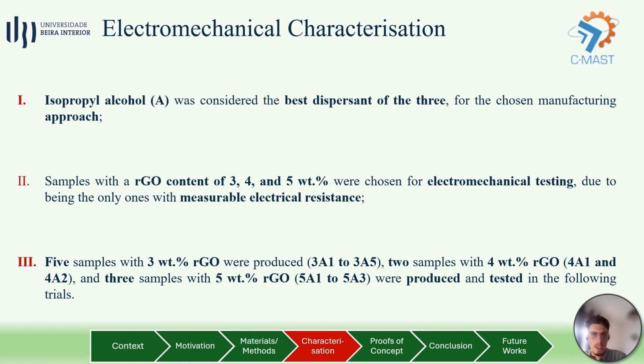Shifting to the electromechanical characterization, the chosen samples were all produced with isopropyl alcohol as a dispersant. The rGO content ranged from 3 to 5 wt%, and in total 5 3% samples, 2 4% samples, and 3 5% samples were tested in the following phases.